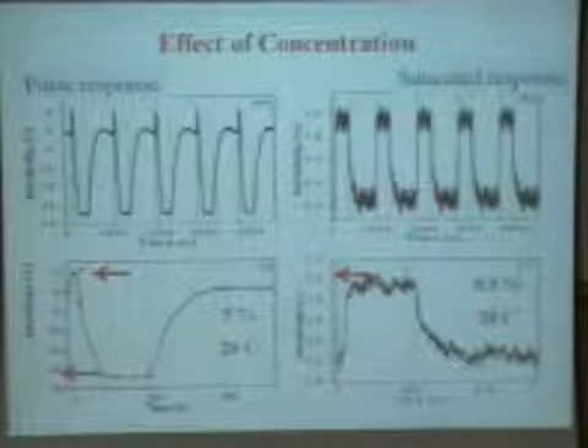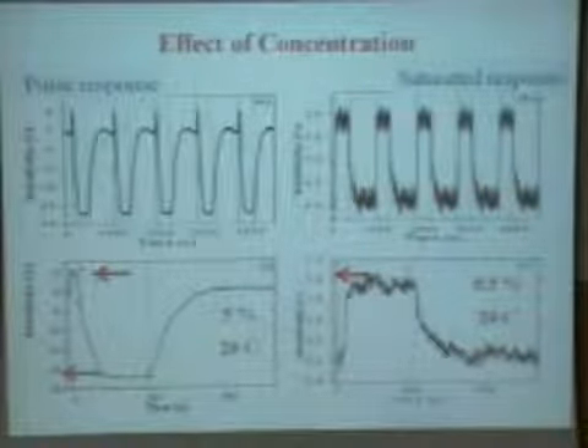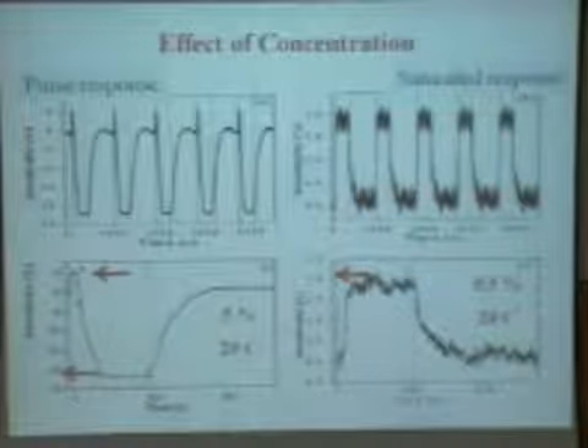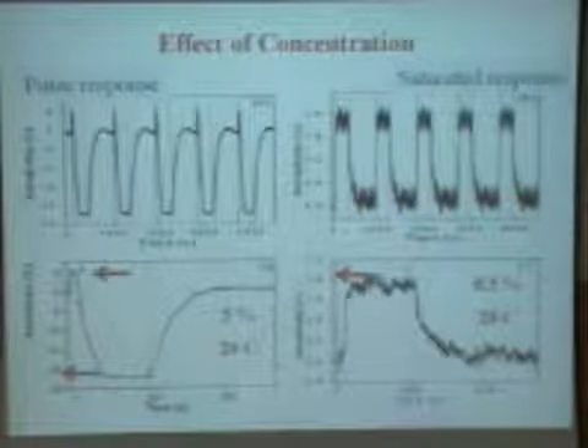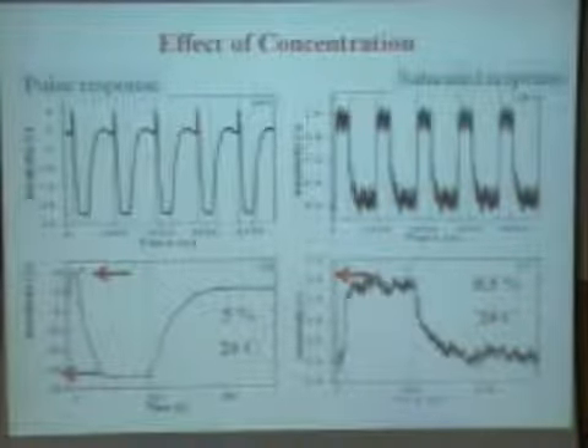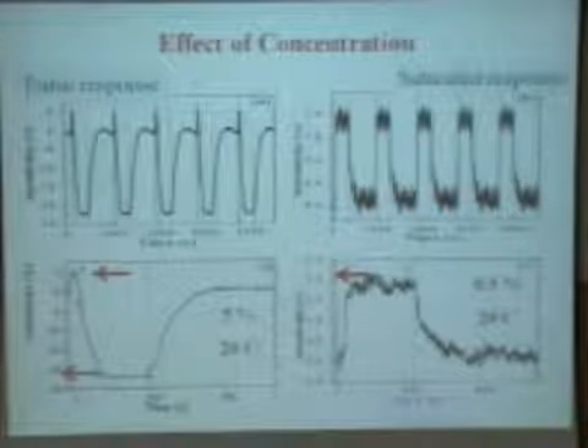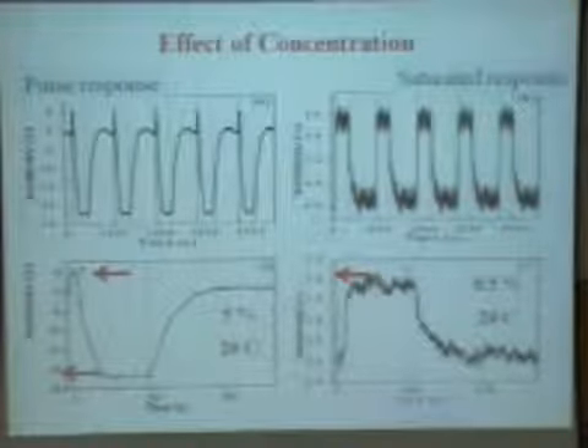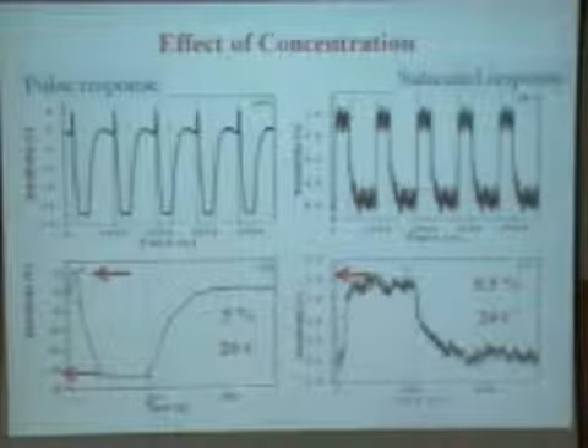And these physical processes, they change. What are these physical processes? The adsorption of hydrogen. First, the hydrogen molecule has to get attached physically to the palladium surface. Then chemically, chemisorption takes place, and the hydrogen molecule gets converted to atomic hydrogen. Then this atomic hydrogen diffuses into the palladium structure, gets incorporated in the palladium structure.